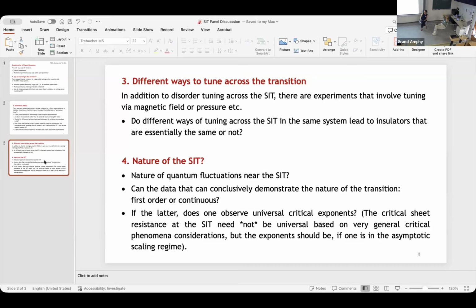For instance, the superfluid density I showed drops till HC2. You did not pay attention, I did not insist on that. But the very last point gives a superfluid stiffness, which relates to the Josephson energy, of about 15 millikelvin. So 15 millikelvin in terms of current is 1 nanoamp. Do you think it's easy to measure a superconductor with a current of 1 nanoamp? In transport, I think it's nearly impossible.